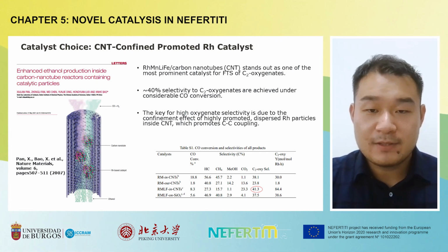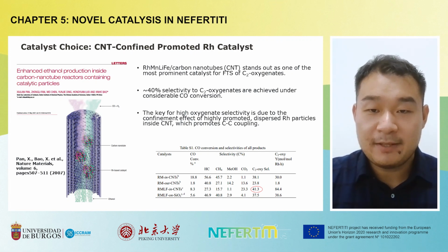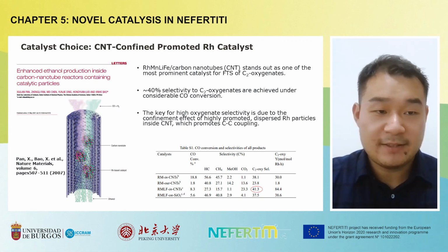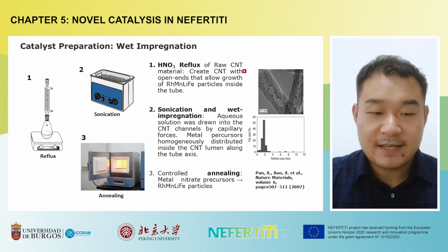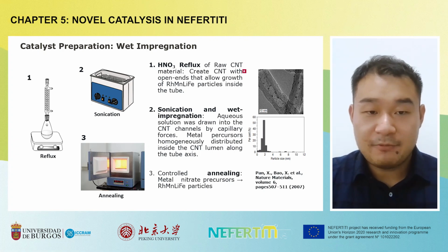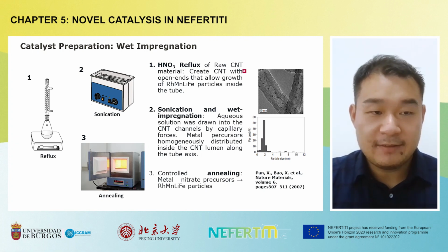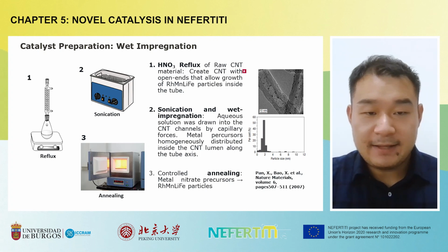And the key for high oxygenate selectivity is due to the so-called confinement effect of the highly dispersed promoted rhodium particles, with ingredients such as manganese, lithium, and iron inside the carbon nanotube that promote the C-C coupling and the formation of C2+ oxygenates. So in this work, we take advantage of this catalyst and we first try to replicate the literature.